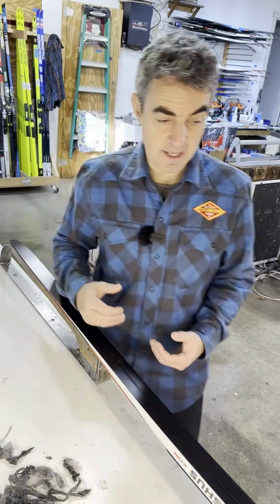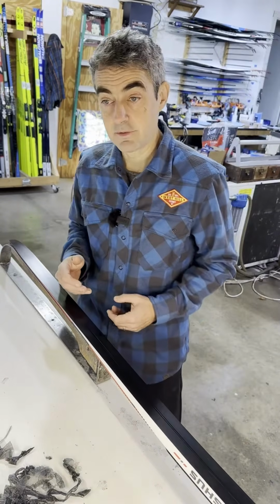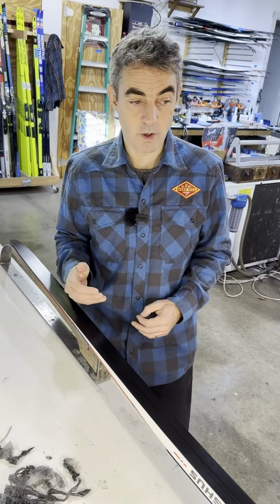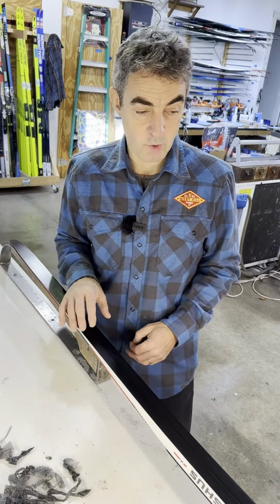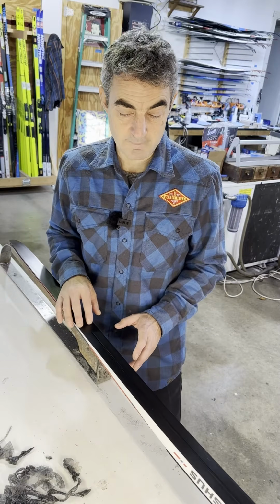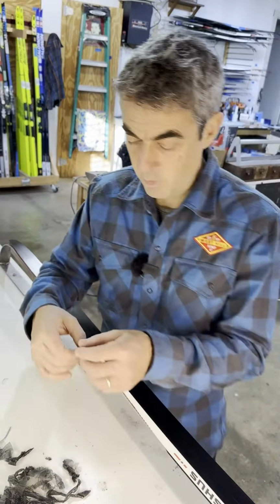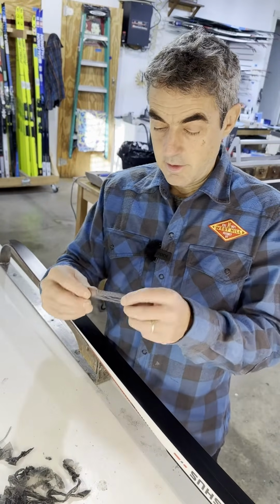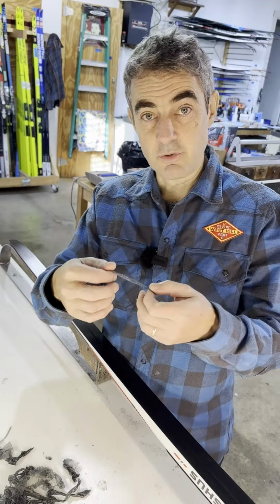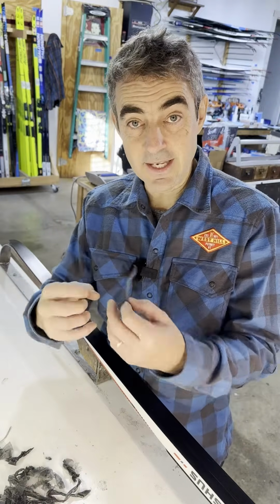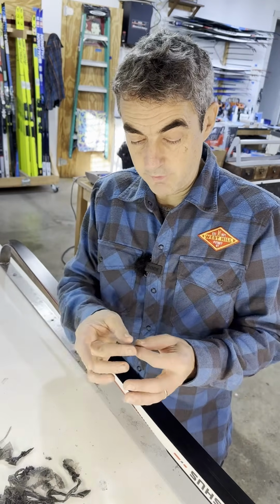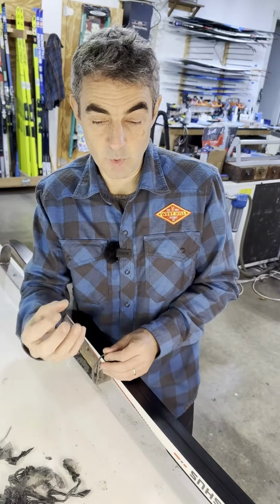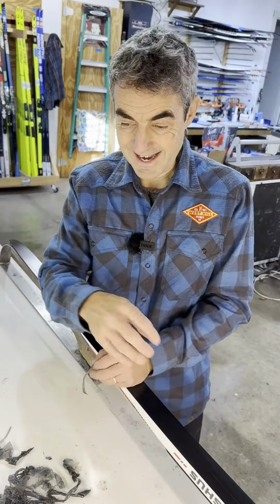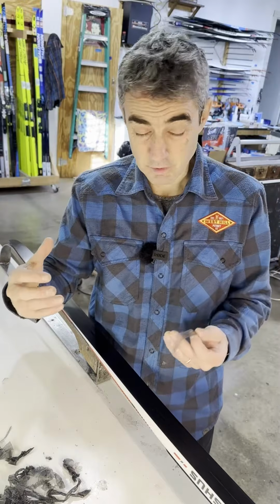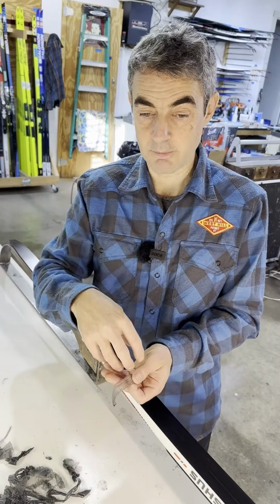You want to try to get the best out of your bases, and for me, for the time being, unless I've seen more than I've seen so far from strictly cold applications, that's going to involve some heat. So how does it work? Let's talk about it. When we have the base material up in that temperature range where it starts to move, it starts to get excited, it starts to expand in the amorphous materials, and we have wax in a molten state, the wax can very, very rapidly sink into the base material, and it happens pretty much close to instantaneously to the depth of the temperature penetration.